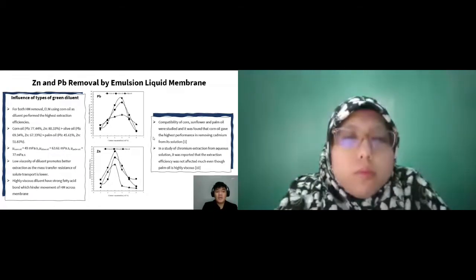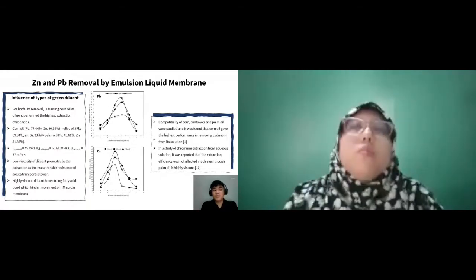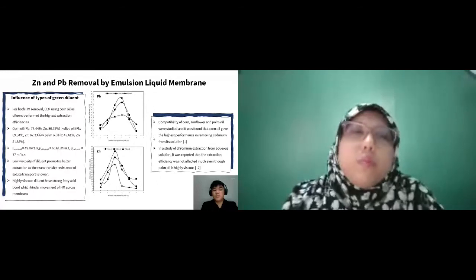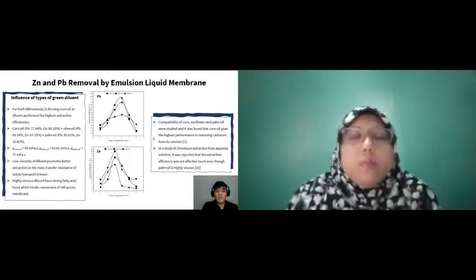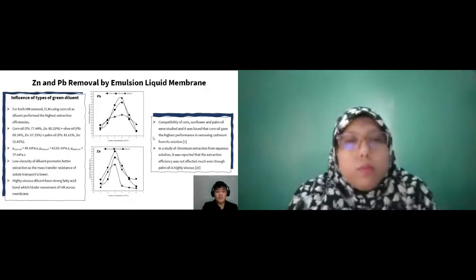It can be correlated that low viscosity of diluent will result in higher heavy metal extraction and vice versa. Higher emulsion viscosity will increase the mass transfer resistance, which hinders solute transport. It will cause coalescence of the internal phase droplets, resulting in lower interfacial area and swelling of the emulsions. Consequently, the emulsion will become unstable and the emulsion liquid membrane becomes inefficient toward heavy metal removal.